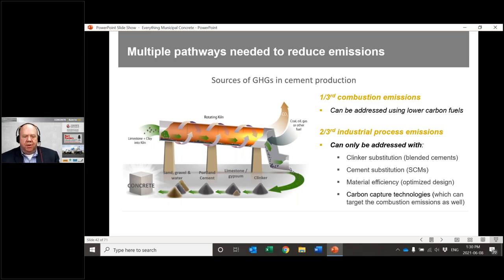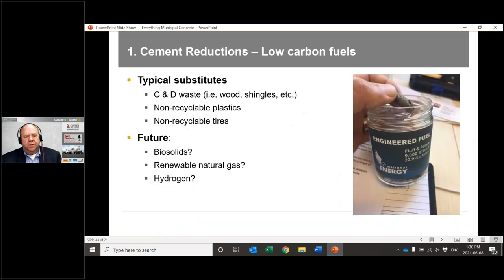The other major component, the two-thirds from that chemical reaction, we have to look at what can we do to try and reduce that. So again, we can look at blended cements, supplementary cementing materials, a few other things. There's a lot of research that's going on into carbon capture. So in the cement industry, they don't estimate what their CO2 emissions are. They actually measure them. And there's a lot of active research projects that are out there looking at how can we capture the CO2 and then use it in another chemical process. So that's a huge opportunity for reductions.